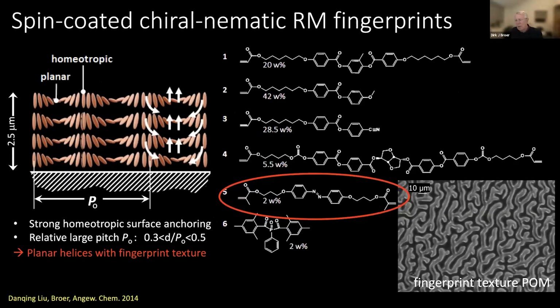Now I would like to go back to the initial system that we studied also with Ben Feringa, where we had the fingerprint texture. So here, again, by controlling the thickness of the film and the interfacial phenomena at the glass surface, by applying a very strong homeotropic anchoring material, we create these fingerprint textures again. And in the fingerprint textures, because of the presence of the azobenzene, upon actuation, you might expect, when the order parameter is decreasing, that we will have expansion in the planar area of this film, and we will have contraction in the perpendicular area. At the same time, it also exerts stress forces on the planar area again.